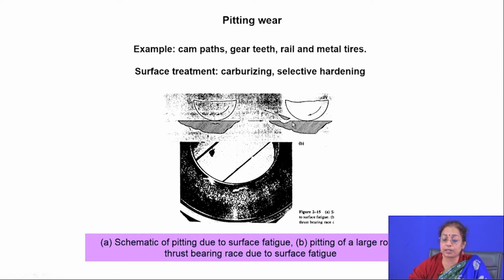If the component has a coated surface, then at the interface there is pit or crack initiation. If it is a composite, then at the interface between the second phase and matrix there is crack initiation, and as soon as the crack initiates it propagates at a much faster rate, causing chip formation, and then material gets removed. So, after the end of the wear you find a lot of pits on the surface.